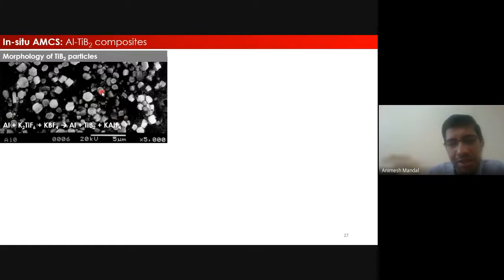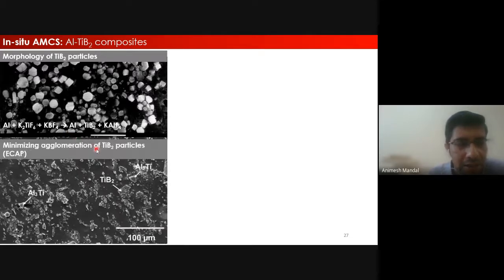The only issue with these in situ composites is that yes, the particle sizes are really fine, but the problem has been agglomeration. These particles tend to agglomerate with one another, and as a result, people have devised certain techniques by which you can at least minimize the agglomeration. For example, if you do certain plastic deformation like equal channel angular pressing, you can break those agglomerates and disperse them within your matrix, and as a result, you can expect better mechanical properties.